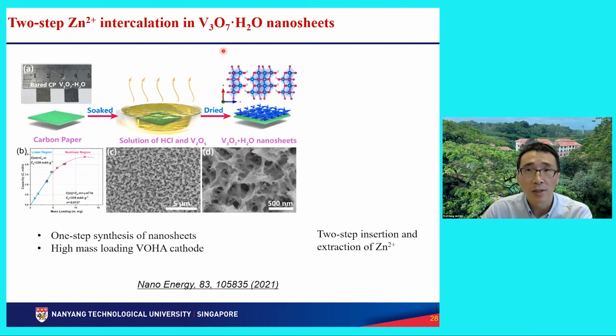The other example is this vanadium oxide. Okay, vanadium oxide hydrate nanosheets. So we can use a hydrothermal method to grow very dense network structures. This is a 2D structure. It's nanosheets. It's a highly dense 3-dimensional porous structure. 3D porous is good. We can also go to high mass loadings, about 5 milligram per centimeter square. This is quite good mass loading, but not a very dense array. There's micro porosity, so that electrolyte can still penetrate into the atoms.